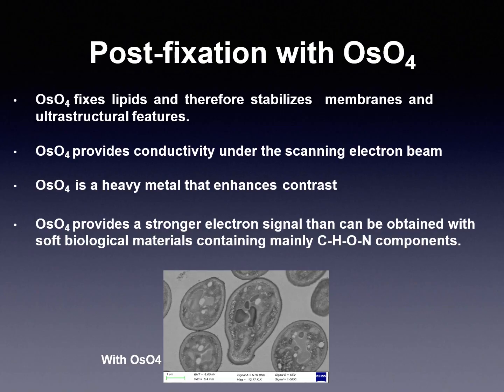Post-fixation with osmium tetroxide. Osmium tetroxide fixes lipids and therefore stabilizes membranes and ultrastructural features. Osmium provides conductivity under the scanning electron microscope. Osmium is a heavy metal that enhances contrast, therefore providing a stronger electron signal, than can be obtained with soft biological material containing mainly carbon, hydrogen, oxygen, and nitrogen components.